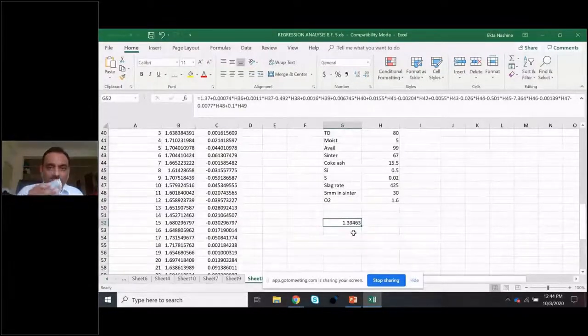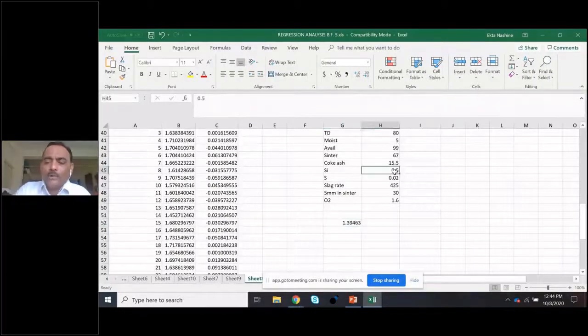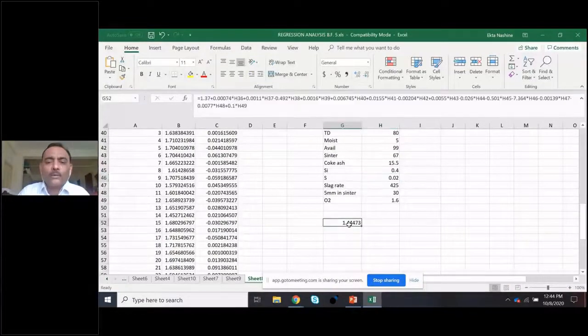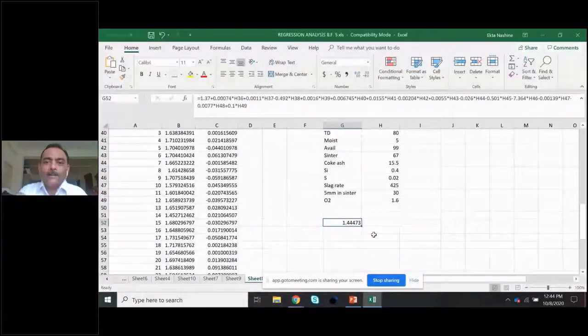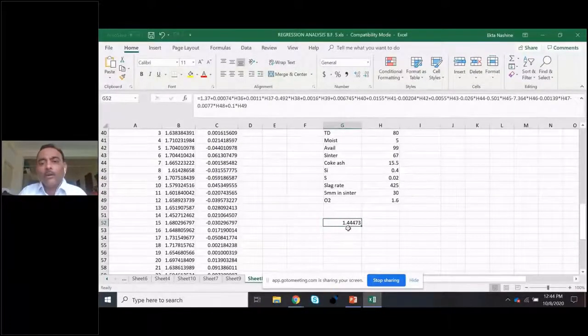Now comes a very beautiful part from this regression analysis. The formula is showing in the fx bar. Suppose somehow I'm able to produce my hot metal silicon instead of 0.5, 0.4. See what happened. The productivity changes to 1.44. So these are the factors, so many factors. When multiple linear regression we have done, silicon able to reduce from 0.5 to 0.4, my productivity rises from 1.39 ton to 1.44. What it shows, lower silicon in hot metal will produce more.